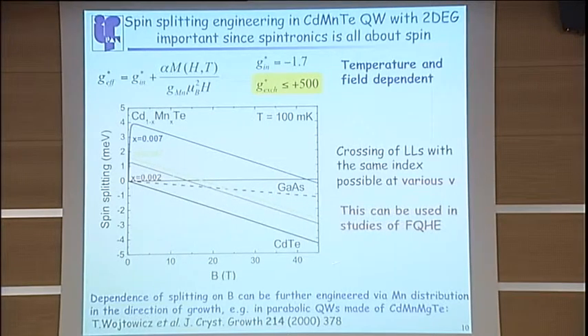You can think about using this for the studies of the fractional quantum Hall effect, and there has already been a poster about this at this conference. And this comes because the intrinsic g factor is negative. The exchange g factor, which is proportional to the modified Brillouin function, is temperature and field dependent. And then, if you apply a low temperature and magnetic field, this part saturates, and then the spin splitting is given by the intrinsic g factor, so you can get also the crossing of the spin up and spin down levels.